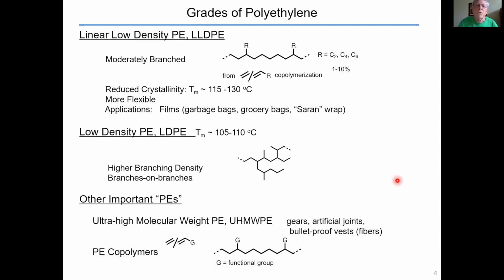There are several grades of polyethylene, and in addition to high density polyethylene, there's so-called linear low density polyethylene. This is a material that's lightly branched, and so the Tm is reduced from about 135 down into the 115 to 130 range. The branches along the chain make this material more flexible, less crystalline. Primarily, this would be used, for example, for garbage bags, grocery bags, Saran wrap. And there's low density polyethylene, which is more highly branched with an even lower Tm, and I'll show you where that comes from in a minute.